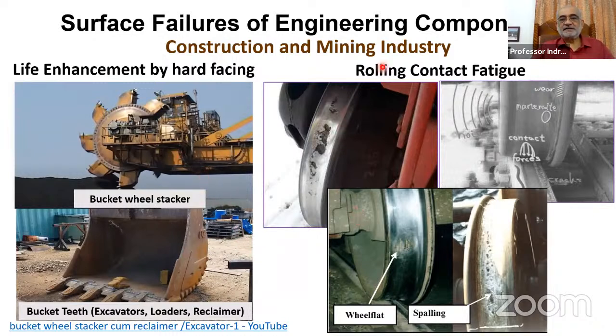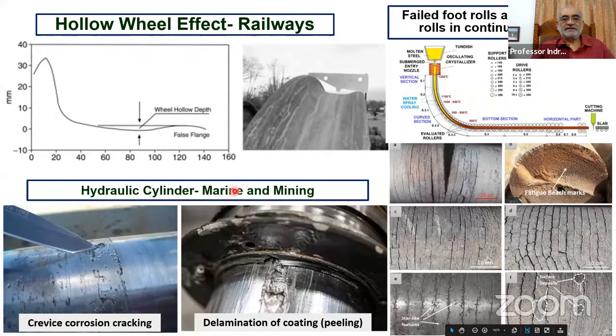But if this whole thing can be remanufactured, then the earth moving industry and mineral processing industry or mining industry will enormously benefit. Similarly, look at these rolls or the wheels, where the rolling contact fatigue is the key reason for damage and life reduction, be it for wheel flat or spalling kind of a damage occurring onto the flat but curved surface, but with a smooth contour. So these chip off portions happen because of cold welding, and in some cases because of the fatigue damage, rolling contact fatigue damage happening over a period of time. Similar things is true for, say, hydraulic cylinders, which is a very common component in the marine propellers or the mining components. Even hollow railway wheels, these damage in the top part clearly shows that this damage occurs over a period of time and progresses. And that exactly is the reason why these need early replacement.